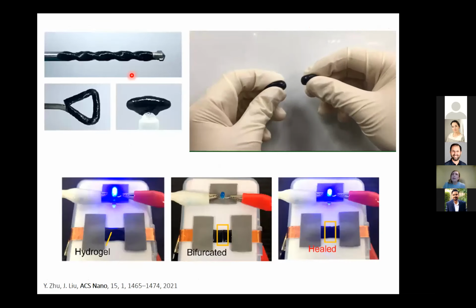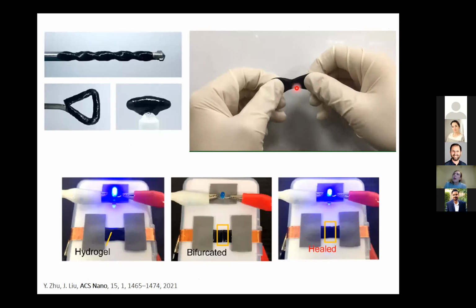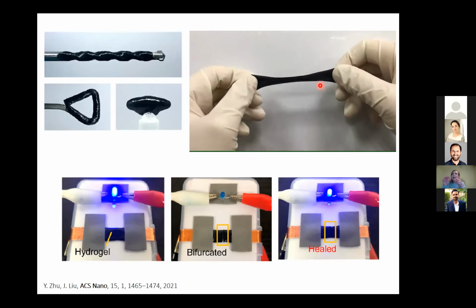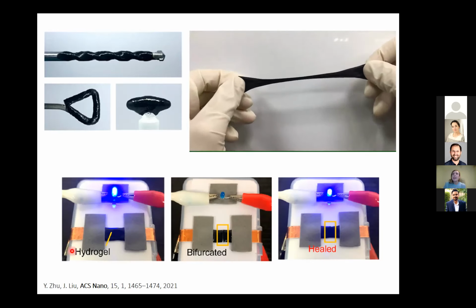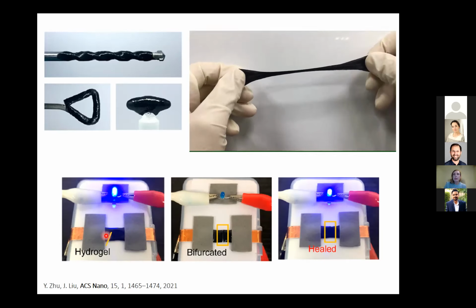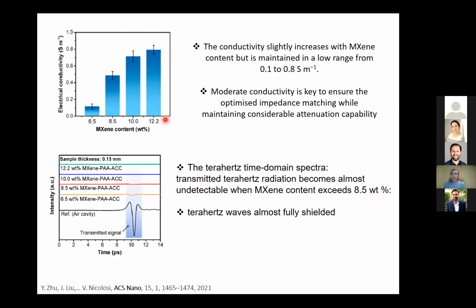For example, here you can see how self-healable they are. You just need to join two pieces of this, and they self-heal. And here is the self-healing happening when you put contacts down. Here it's one stretched composite, then you cut it down and you bifurcate it and you break the circuit, and then it self-heals within seconds. What is nice is that you can give it the shape of the material you want to shield. And this has been a great advantage, because one of the things we saw that really works for this material is how we can shield radiation.